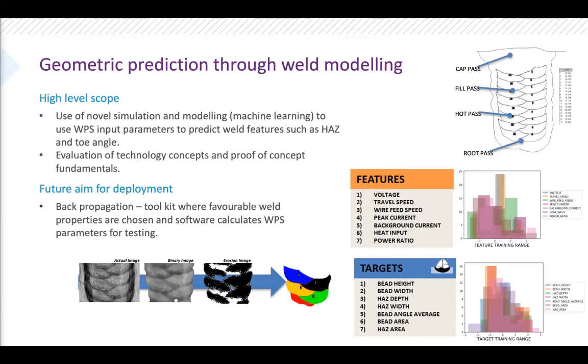So the other low TRL application that we developed and evaluated through the course of the project was the use of neural networks for modeling of welding processes. The concept behind this work was establishing your input parameters into the welding process. So essentially your welding procedure, your specification of material, your filler, your welding parameters, conditions leading into the process, and then you can correlate that to key parameters around the weld that's output. So for each pass, finding out the weld thickness, the size of the heat affected zone, the penetration, the toe angle between the deposited weld and the wall and the subsequent layers. And then as you can build up that model and increase its accuracy for your selected process, you can then start looking at back propagation of that neural network.